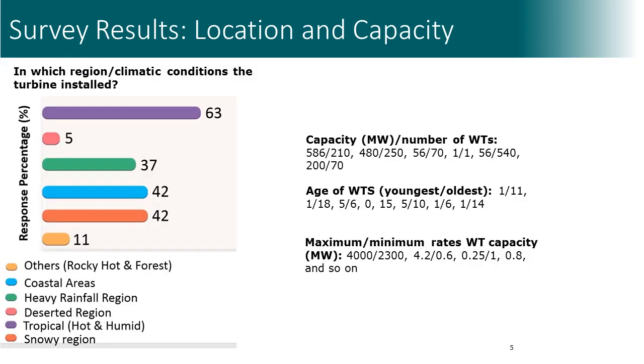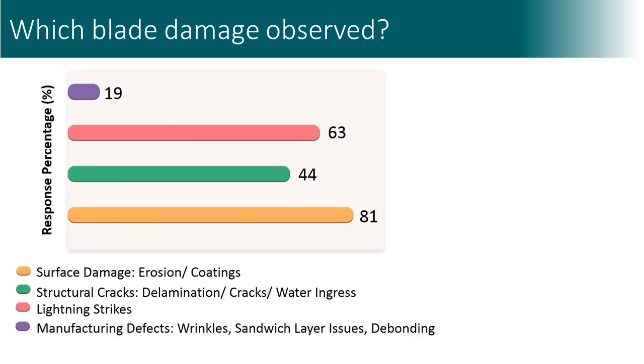The first question was where and under which climatic conditions the serviced wind turbines are installed. You can see that we have observations both from Europe, including snowy regions, and from India. The age of wind turbines in the parks ranged from 1 year to 14 or even 18 years. Which blade damage mechanisms are observed? Most often, surface erosion is reported. But lightning strikes are also observed quite often.